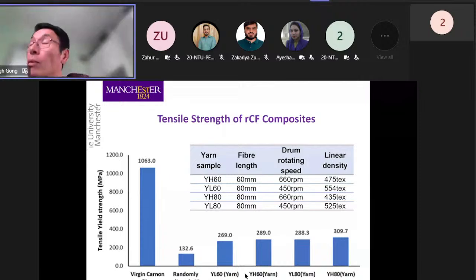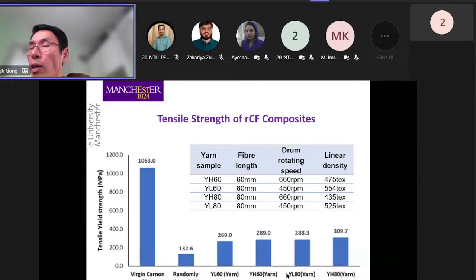However, the fiber volume fraction within the spun yarn composite is much lower. So relatively speaking, the strength is actually not that bad. Compared with randomly aligned, in other words non-woven, composites, it's much better anyway. So we can improve it, but again, as I said, there is still plenty of work to do in this aspect. We are still working.